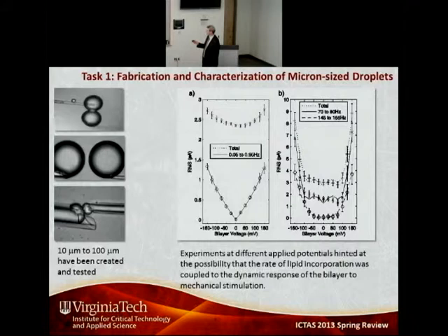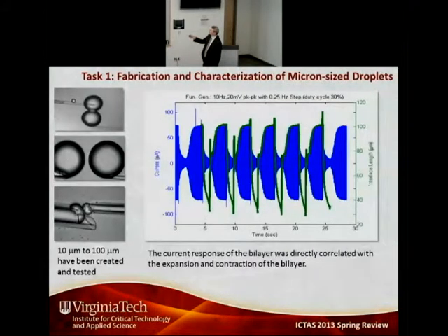Now, most of the attempts, starting with Majumdar's attempt about 6 or 7 years ago, have focused on solid materials. So what people have done is, for instance, they have started to dope materials to introduce asymmetry. So for instance, a carbon nanotube might be pure carbon at one end, but you might have carbon isotopes in it. So it's C12 at one end, and as you go along the carbon nanotube, it's perhaps C13 or C14 at the other end.